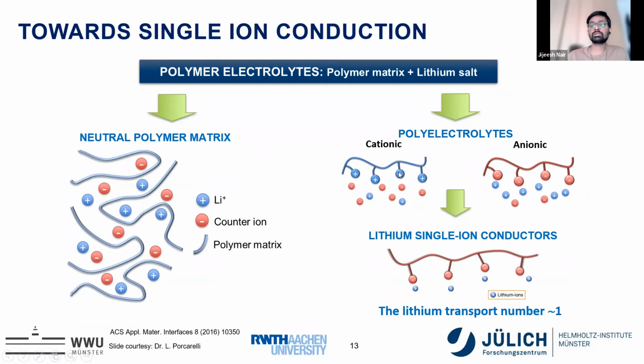Either it is a positive charge in the case of cationic polyelectrolyte, or an anionic polymer electrolyte in which the backbone is negatively charged. And especially in the case of anionic polymer electrolyte, when the positive charge is lithium ion, the only species that is moving in a polymer matrix is lithium ion. This lithium ion can move within the electrolyte where the anions are mostly immobile. This is one of the reasons that you can get a very high transport number, which is very close to 1, where only lithium ions are moved.